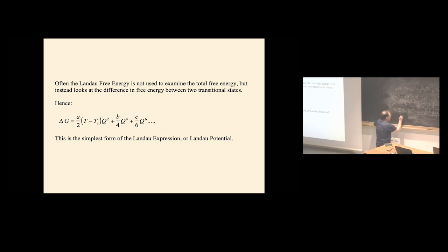Okay, so Q can either be, what was it? Minus B plus B. That'll be 0. Or Q squared can equal minus B minus B, so minus 2B over C. Okay, but this is at the same temperature. This is at Tc. So it's not like it can be one or the other. It's both. So when you plot this out as a function of temperature, you hit Tc. You've got your Q plotted here.